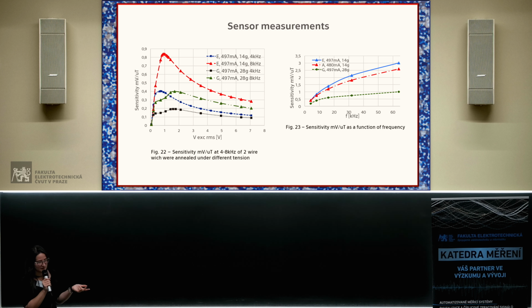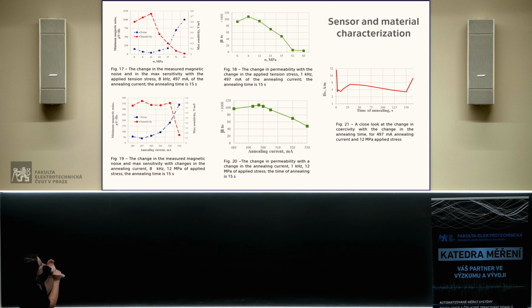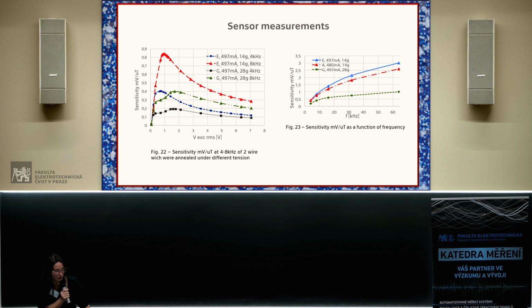And what we could say is that this change of stress is quite dramatic, because sensitivity is almost twice higher for the wire with lower stress. But when we apply even lower stress, the results are worse. I can show you previous graphs when stress was lower than 14 grams, 12 megapascal. So it's an optimum point for this certain wire, when applied stress is 12 megapascal, and this current is also the optimum current, 497 milliamps. But this characteristic is flatter for the wire with higher tension, which could be used in some sensors where stability is more important than sensitivity.